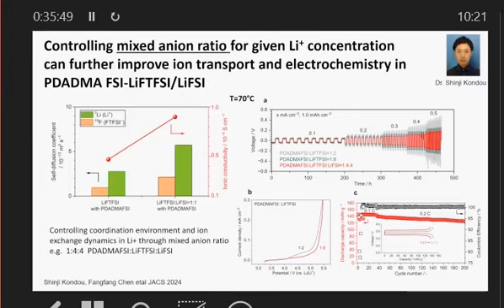And again, we put it into an LFP cell again, and we found good stability. So it does work as a battery electrolyte in a lithium metal, solid state cell. This is just really a small part of the composition range that we've talked about. We've got a lot of room to play with here, which we haven't even considered yet. We've just looked at 2 different compositions here, and this might not be the optimum. So from the applied sense, this is where AI might come into it a little bit more, to help us choose what might be the optimum composition to give us the best performance in these systems.